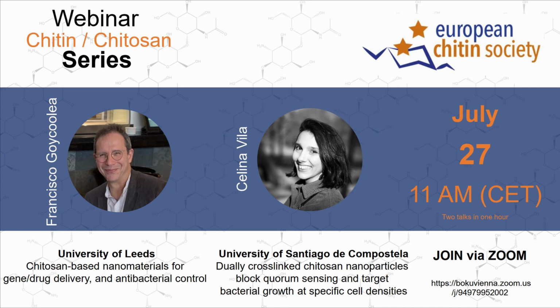If I might just quickly comment here, yes, definitely the size, Carla, is important. We've tried to model that in the simulations we did. We just assumed that all the capsules were of the same size, which of course is not a reality. So we know they are highly polydispersed, but we think that the size plays a role because that actually determines how many particles will bind at the surface. And if you consider polydispersity, larger particles together with the smaller ones will fill out all the void spaces. So this is very relevant in paints, for example. It's not interesting to have all the particles of the same size, but to have polydispersity, and then the coating is much more efficient. But that's definitely something we need to investigate further.